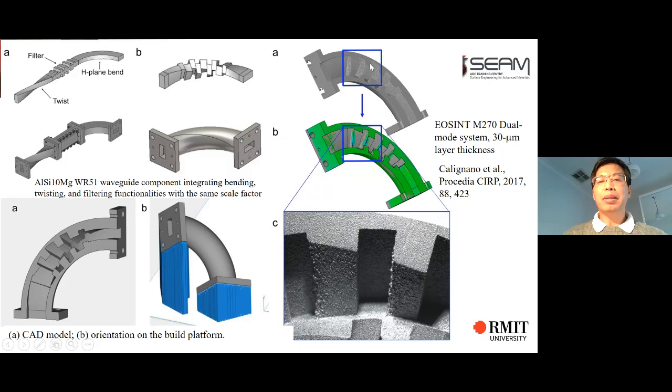This is the internal part. And if you can see this one, that's the downward facing surface. Internal downward facing surface. You can look at that, the very, very rough surface. Unfortunately, I think this part is not subjected to cyclic loading. As you can imagine, if this is subjected to cyclic loading, this could become the weakest part of the component. That could become problematic. The surface finish is quite different, and it's mainly due to this part being a downward facing surface.